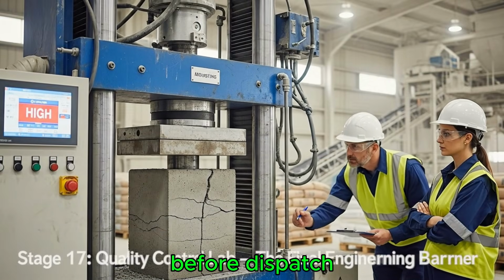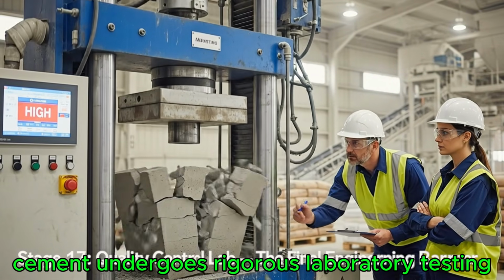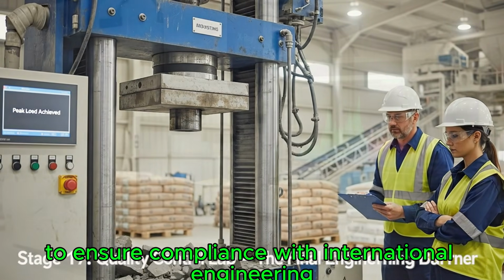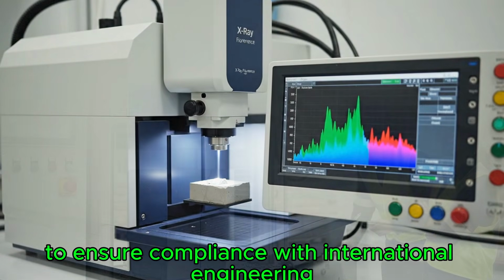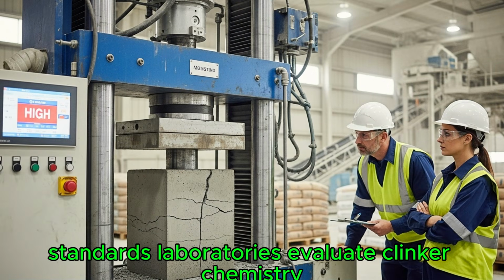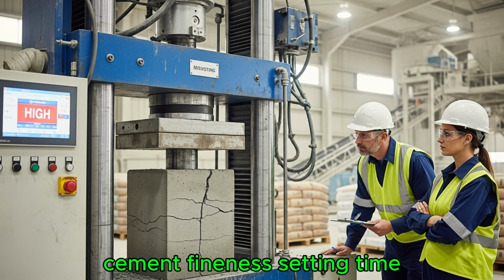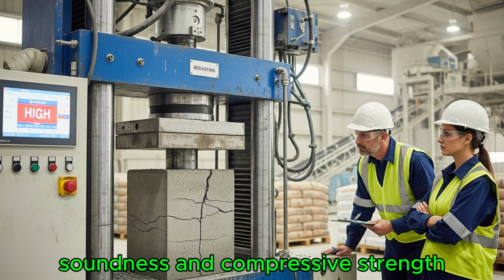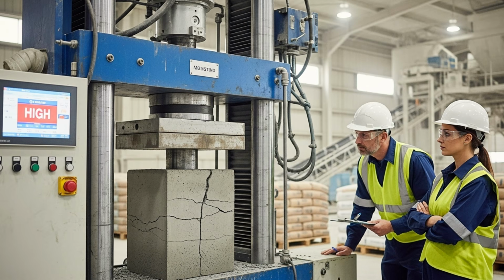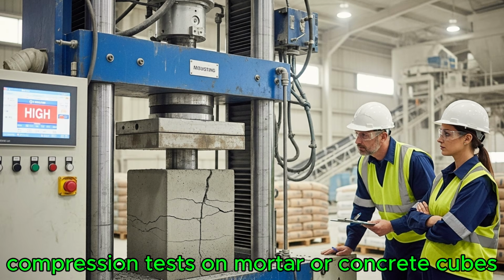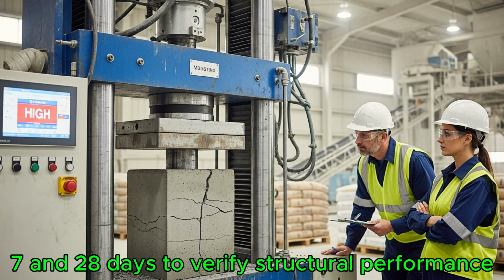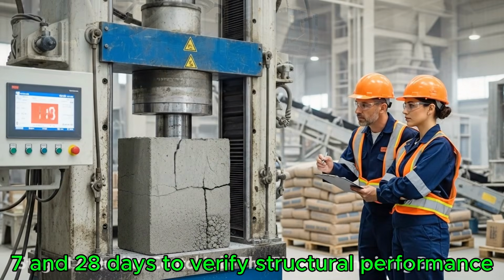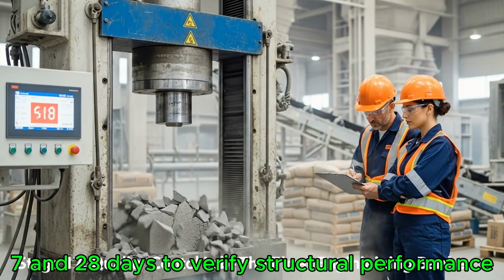Before dispatch, cement undergoes rigorous laboratory testing to ensure compliance with international engineering standards. Laboratories evaluate clinker chemistry, cement fineness, setting time, soundness, and compressive strength development. Compression tests on mortar or concrete cubes are conducted at 3, 7, and 28 days to verify structural performance.